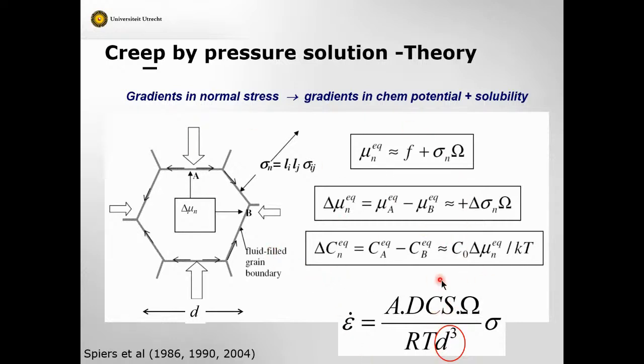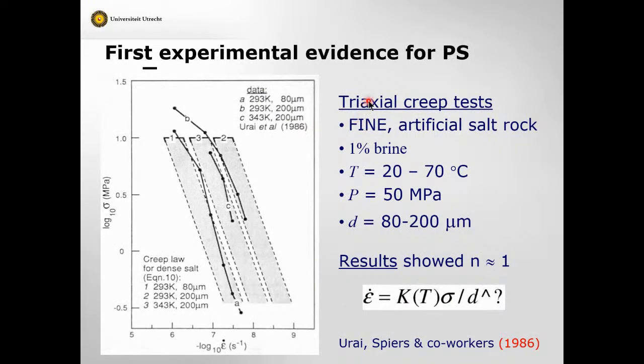And you can derive from thermodynamics and kinetics a creep law off of that. Of course, the faster it dissolves and precipitates, the faster the stuff creeps. And it takes this form where the strain rate is linearly related to the stress, inversely related to the cube of the grain size, and this term here, DCS, describes the diffusive properties, the ease of diffusion in grain boundary fluids. Okay, and you only need a few tens of ppm of adsorbed water to get this effect, in theory. So this is all theory.